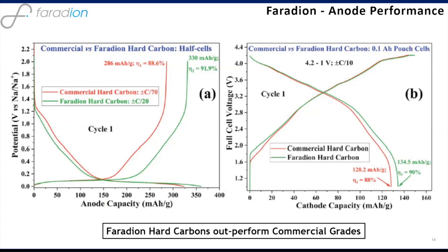So we're running at a reversible specific capacity in a half cell of 330 milliamp hours per gram with good charge efficiency in the first cycle. 330 milliamp hours per gram is very similar to what you would get delivered from a good crystalline graphite in a lithium ion application. So it's good performance.